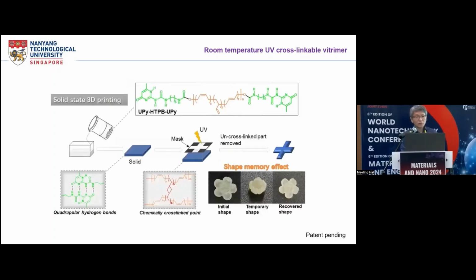Room temperature UV cross-linkable vitrimer. She developed the formula for this particular vitrimer. The vitrimer has excellent shape memory effect, which means that upon heating it is able to recover its original shape. I have mentioned the importance of having this shape memory effect in this solid state cross-linking.